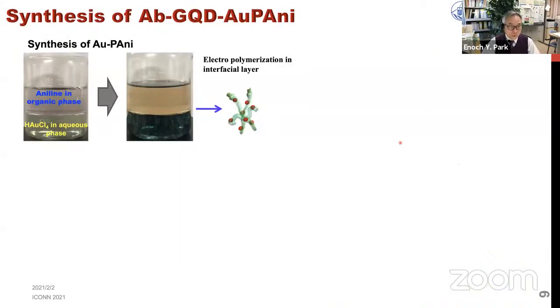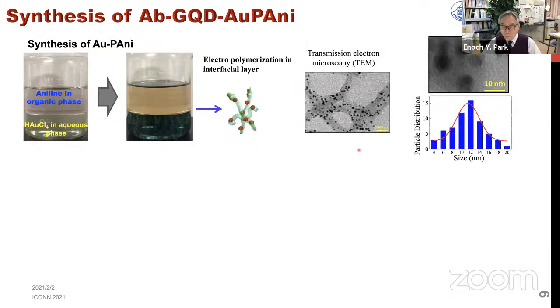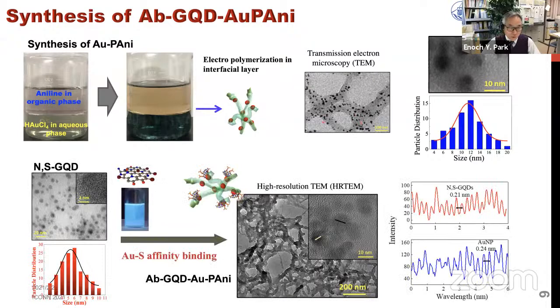The synthetic method is very simple. We use electropolymerization and the interfacial layer method, with aniline in the organic phase and chloroauric acid in the aqueous phase. We synthesize the material and confirm the morphology and size here: almost 10 or 12 nanometer size, nanowire morphology. NSGQD was synthesized by a conventional method. This is the final synthesized NSGQD, and we conjugate antibody on its surface, and this material was also bound to the gold particle embedded polyaniline, and we confirmed the gold particle and the quantum dot in high resolution TEM image.